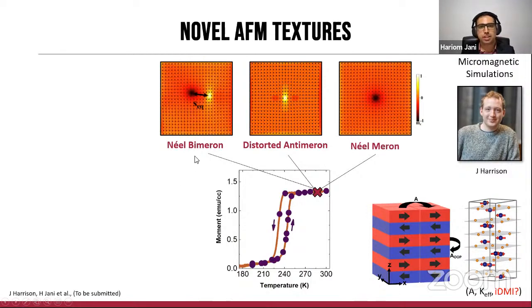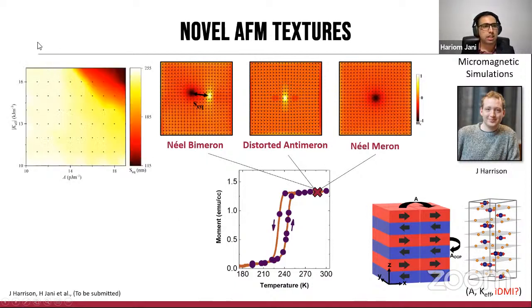Now, if we were to characterize the size of this object as the intercore distance, we can, by varying the exchange and the anisotropy in the system, create a rich phase diagram of what the sizes of these objects could be. And as you can see here, there is very rich control over the dimensions that can be obtained, all the way almost until about 100 nanometer length scale.